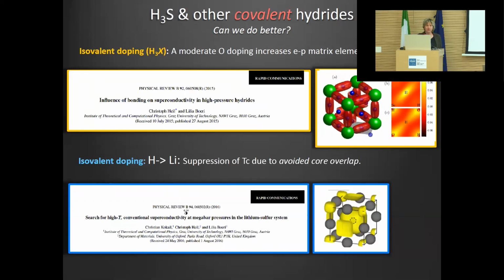And the element which is immediately below hydrogen is lithium. And in principle, again, at ambient pressure, I mean, what matters is the valence. Lithium and hydrogen should behave very similarly. With pressure, this is not the case anymore. And the reason is that we said hydrogen is special because it doesn't have a core, but lithium has a core. And when you put lithium under sufficiently high pressure, you see the effect of the core. And this is shown here. So this is a sketch of a lithium sulfur compound, lithium 3S actually, which forms at high pressure, but it's not superconducting. And the reason is that if you look at the charge density distribution, it's completely different from what you see in hydrogen. So you have here charge density localization, not along the bonds, but in the empty voids of the structure.